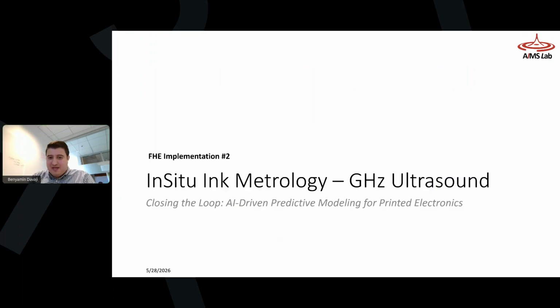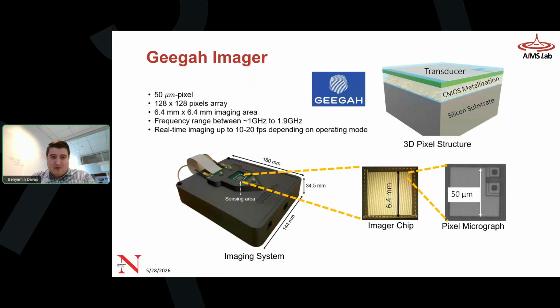The second case of FHE implementation for using AI is to add a new type of sensor and sensorization. And here we collaborated with Cornell and the spin-off from Cornell, Geegah. Geegah is a company that develops these imagers. These are ultrasound imagers. They can measure density, they can measure speed of sound, but they can measure it over a very large array, 128 by 128. Each pixel is around 50 micron, but they do have better versions. The one that we had was around 50 micron. And this is 16,000 pixels.